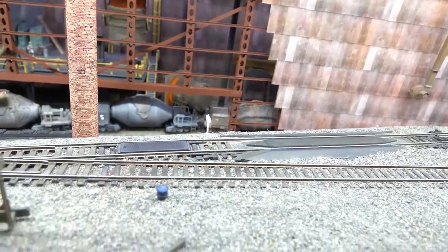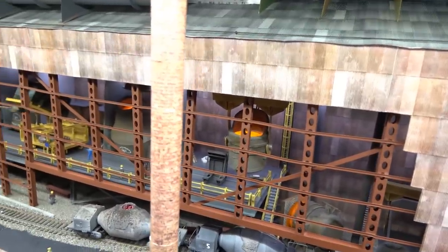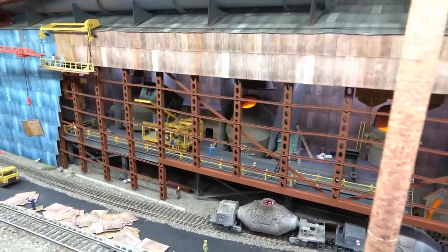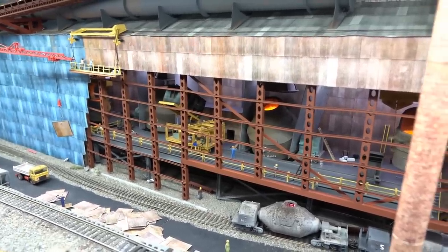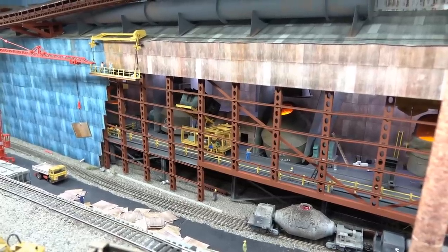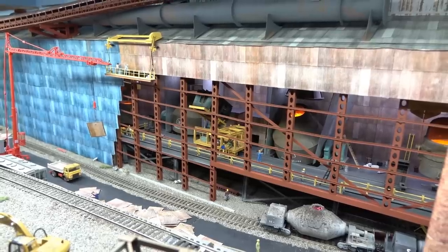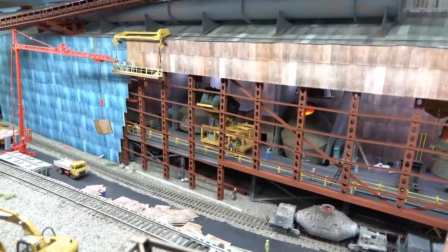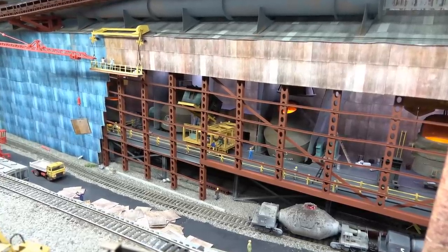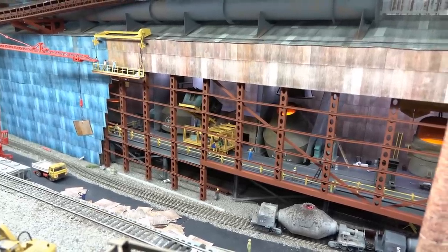Oh, okay, yeah. The ladle gets picked up by the crane. Oh, there's the ladle, okay. Carried through the shop, dumped in on top of the scrap steel. Okay. Then you rotate the furnace back up vertical, bring big oxygen lances down in, and you blow humongous quantities of oxygen, and I couldn't even tell you. 20,000 cubic feet a minute of oxygen. Wow. You blow that in there for 20 minutes. It burns volatile, just extremely volatile down in there. It burns out all the carbon. So now when you're done, you've got molten steel.